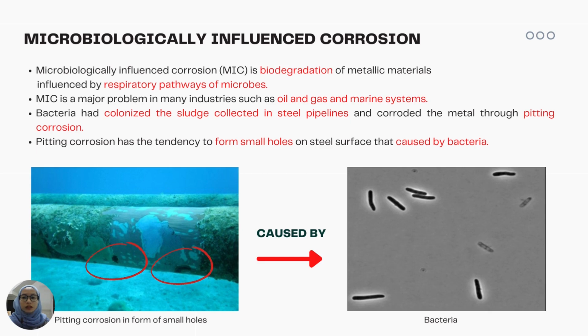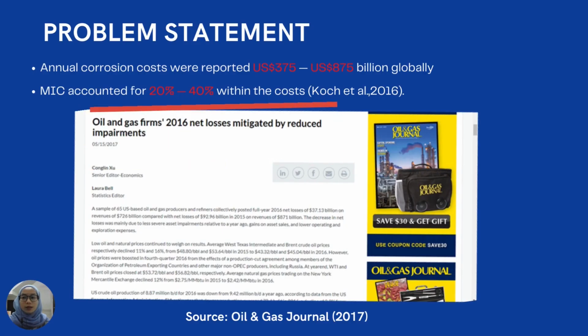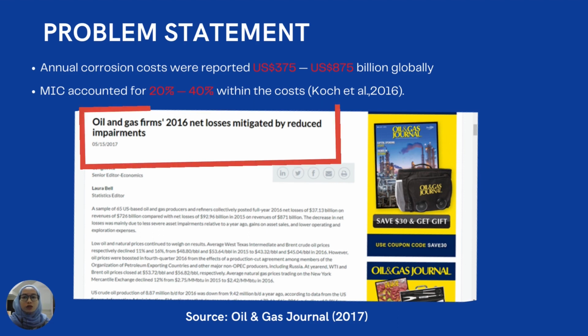It is postulated that the little things, microbes, had colonized the pipeline surface during crude oil transmission, subsequently damaging the metal surface through pitting. Pitting corrosion refers to the formation of small holes on the metal surface caused by the bacteria. At the current situation, MIC is responsible for 100 billion in annual corrosion costs worldwide and accounts for between 20 to 40% of the cost.